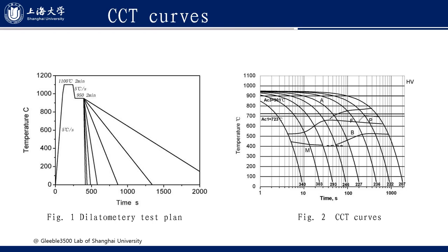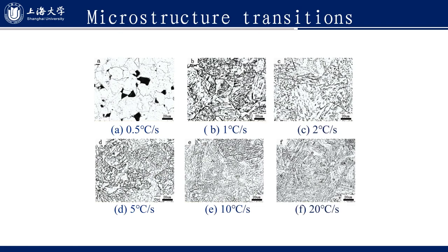CCT curves: the steel was heated to 1100 degrees C, kept 2 minutes, and cooled to 950 degrees C, kept 2 minutes, then cooled to room temperature with different cooling rates. After the test, the specimens were cut in half to investigate the microstructure of the steel. This figure shows the CCT curve of the steel. This is the microstructure transition at different cooling rates.